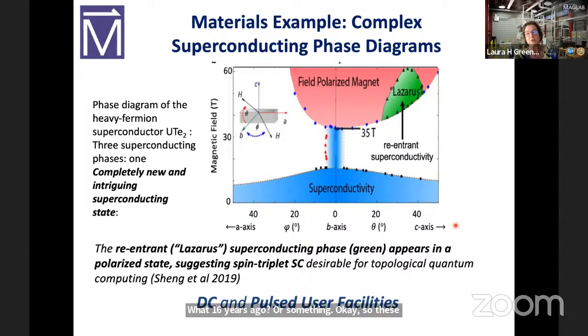These materials, I showed you one kind of complex phase diagram, and this is another complex phase diagram. This was discovered, this is a heavy fermion superconductor. By heavy fermion, we mean that the electrons, if you measure the electronic mass thermodynamically, is very heavy, due to electron-electron correlations. Now, many of you know that below a certain temperature, as I mentioned, electrons are superconducting, and besides the superconducting transition temperature, if you put too much magnetic field on it, either electric field or magnetic field, current or field, you break the Cooper pairs and you force it to become normal. So that's critical field, and most people understand that.